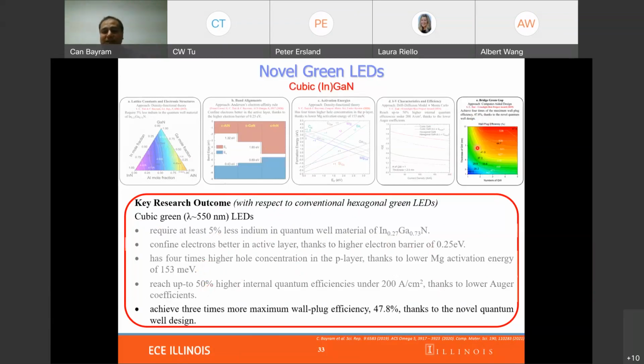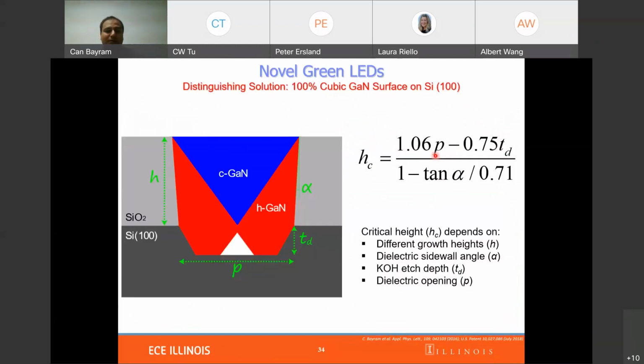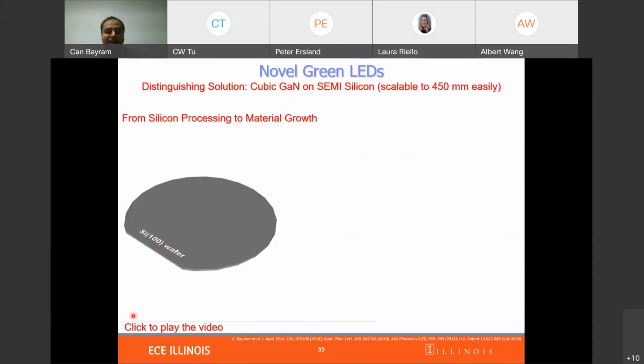And overall, based on our design, you can create a path to LED structures where you emit more light than heat in the green spectrum. So this is very important. This all depends on, of course, the synthesis of a cubic gallium nitride material. This is the structure where we are using what we call a U-groove, where we have the oxide with a thickness H, exposed silicon 111 facet in a 100 wafer, and then a slight sidewall angle, which is based on the process parameter. So basically, if we can design these structures, we can achieve pure cubic nitride systems.